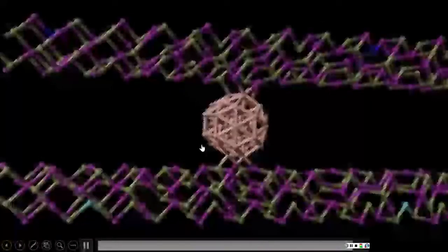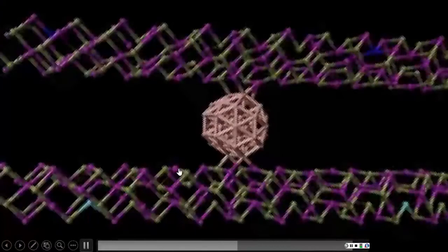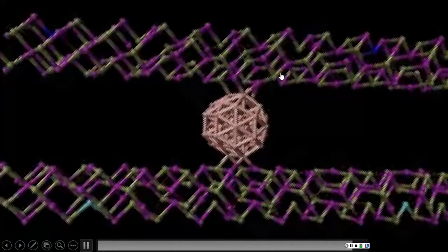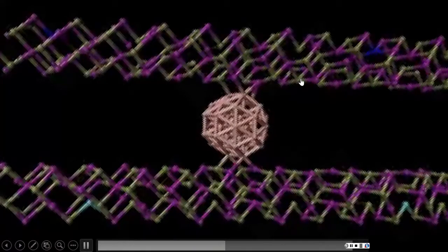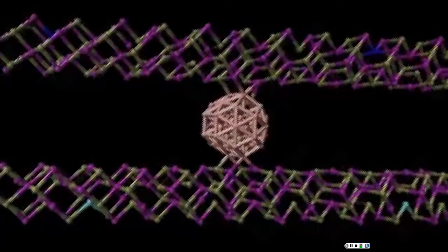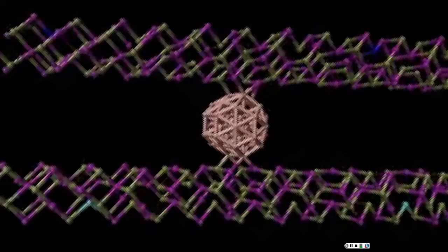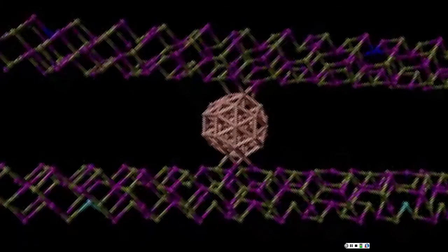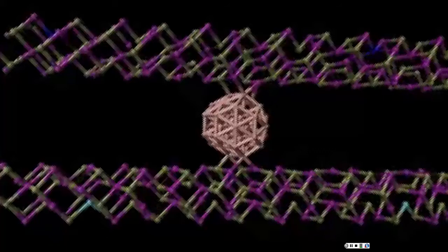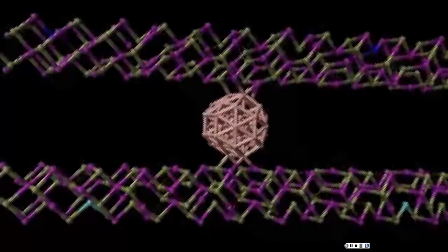Okay, so this is at 3.2 angstroms. It wasn't as interesting, but you can very lightly see the molecule beginning to completely fly apart. The temperature which was studied was 2600 Kelvin, which was well above the melting point of lead telluride, which is approximately 1197 Kelvin, and the gold nanoparticle, it's actually kind of weird that it shrinks a little bit.